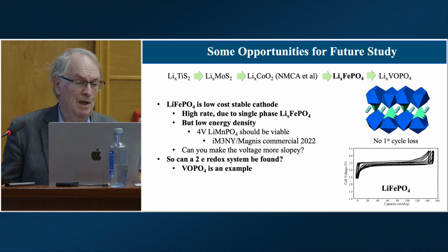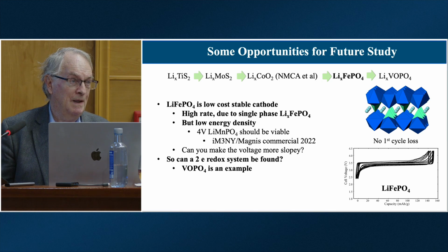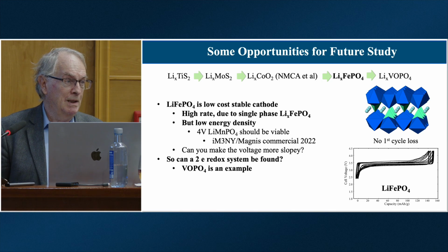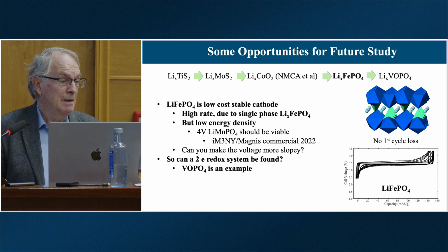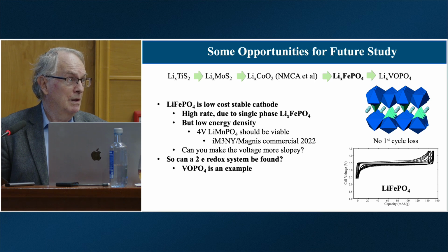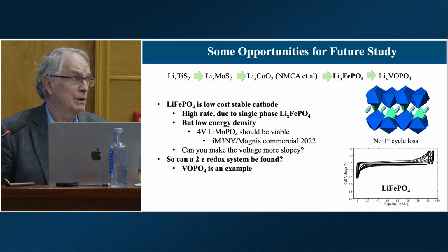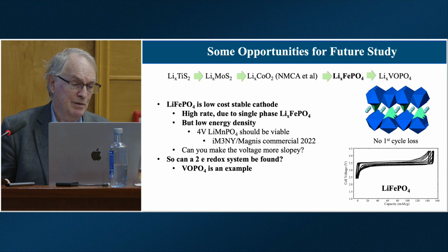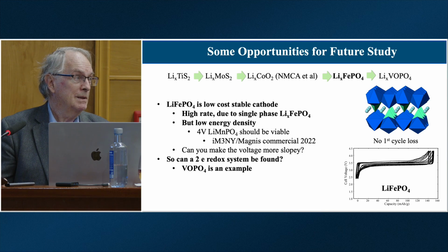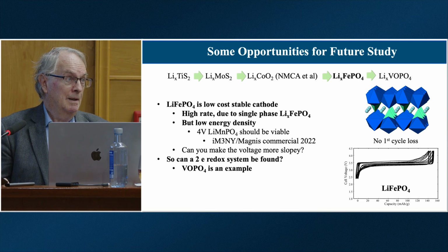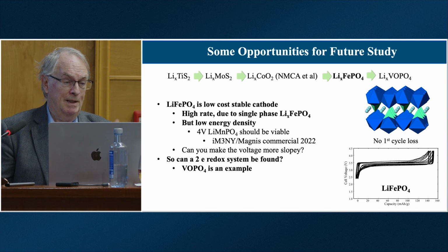As I mentioned, we started out with titanium disulfide. Moly Energy in British Columbia, in Canada, switched and used molybdenum disulfide in place of titanium because this is molybdenite, which they can dig out of the ground in British Columbia. So they, in fact, commercialized that, built up an industry based on that, but then they had some other issues later on. As I mentioned, then Goodenough developed lithium cobalt oxide, so we went there.